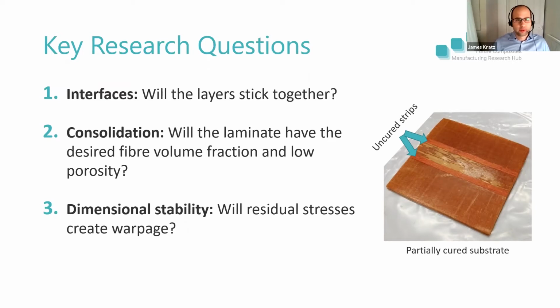So you might imagine that if you've got your first ply oriented at the 0-degree direction, and then it's partially cured, and you put a 90-degree ply on top of that and cure it, once you release the pressure, are we going to end up with a saddle, or are we going to end up with residual stresses that are so severe that we can't continue the process?